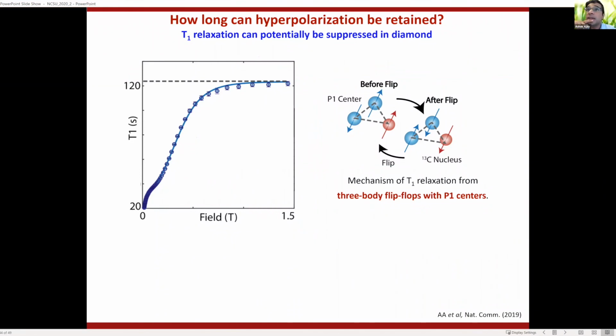And we've done some recent work. It turns out that these P1 centers, which are usually considered to be useless and just lying around, can play a role to accelerate spin diffusion. The P1 is an electron, and this electron has a wider reach in the lattice. So an electron can see nuclear spins even up to 10 nanometers. One nuclear spin can transfer its polarization transiently to this electron, which can then pass it on to another nucleus. And so it turns out that potentially this electron-mediated spin diffusion can be faster than pure nuclear spin diffusion. But this is a difficult question to answer because it's very difficult to see intrinsically what's happening in the lattice. But there are some indications that this process is operational here.